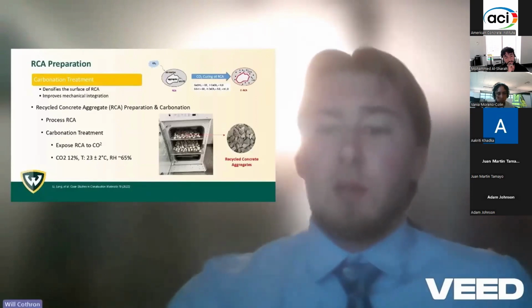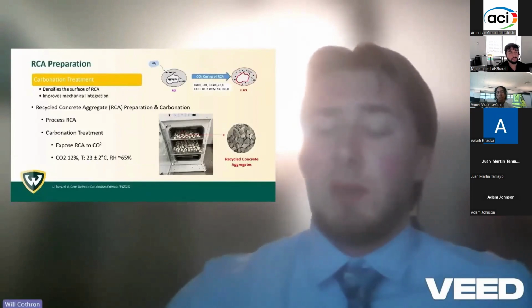Natural aggregates and recycled concrete aggregates need to be washed and dried before adding them to the mix. For the recycled aggregates, once the materials have been dried, they need to be placed into the carbonation chamber for 24 hours to start the carbonation treatment. The recycled concrete aggregates inside the chamber are exposed to CO2 gas at a concentration of 12%, temperature of about 23 degrees Celsius, and around 65% relative humidity levels.